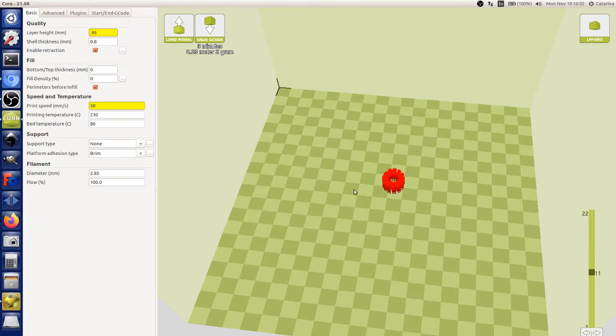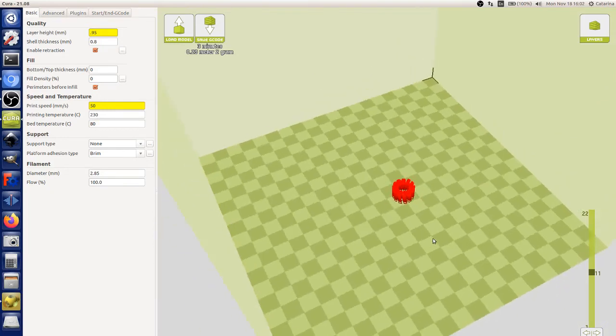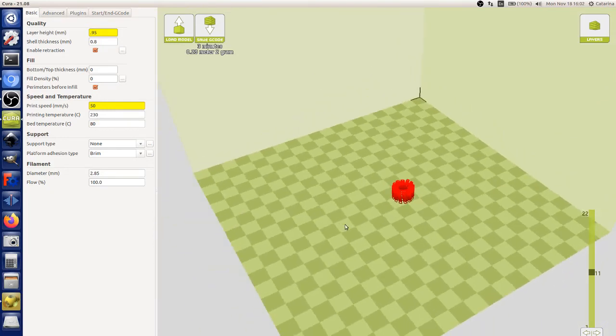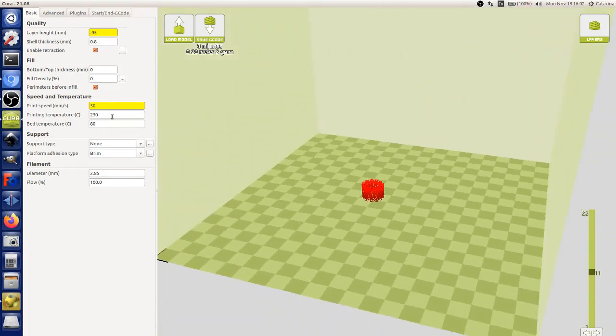So we're talking about PEI surface, which is the industry standard for pretty high quality printing, where you don't have to use any painter's tape or any adhesive substances for prints to stick to the bed. So, we've been doing a lot of 80C, but we notice that if we get it higher, the prints just don't stick to it, which is kind of counterintuitive. I initially thought that, oh, the hotter you get, the better they'll stick. But if you think about it, if you're getting near the melting temperature of the plastic, well, naturally it's not going to stick to the bed anymore because it's just melting off. So with a high-performance print bed, be careful about getting your bed too hot. Print temperature is about 230 in our case.